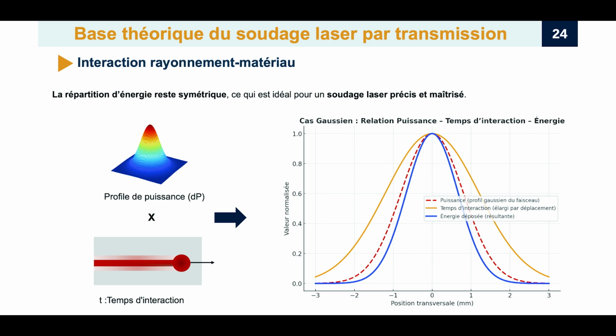And meanwhile, out at the edges of the track, the power P was already low because it's a Gaussian beam, and the interaction time T is minimal. So E equals P times T is incredibly low at the edges. So low, in fact, that the material there probably never even reaches the melting temperature, TF. So the result is a disaster. A burnt, degraded, brittle center and cold, unwelded edges. A completely non-homogeneous weld bead with terrible overall strength. Yeah. Useless. So the standard Gaussian beam is often a non-starter for precision polymer welding in motion.